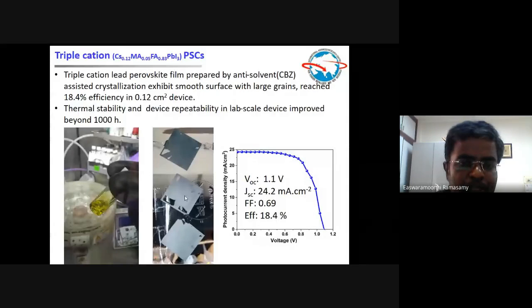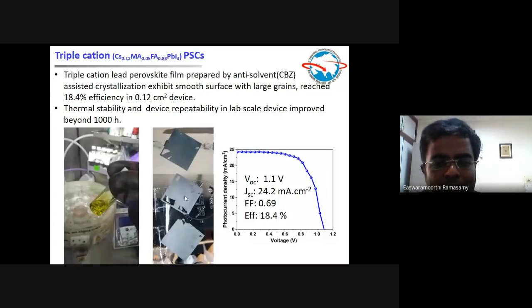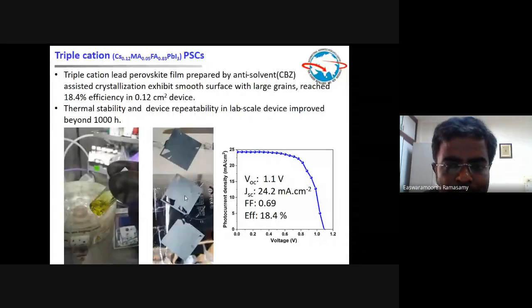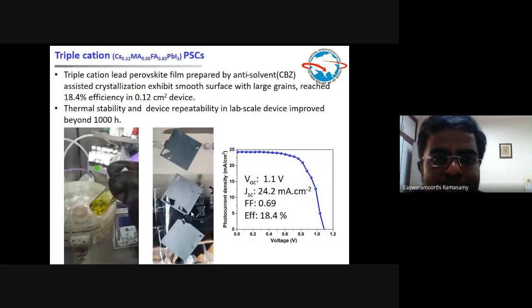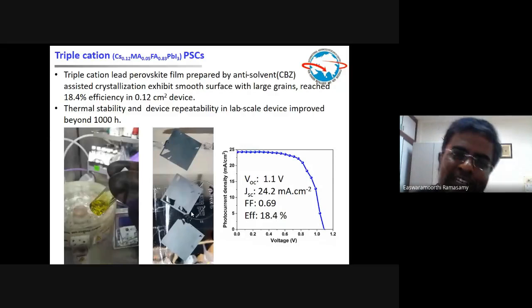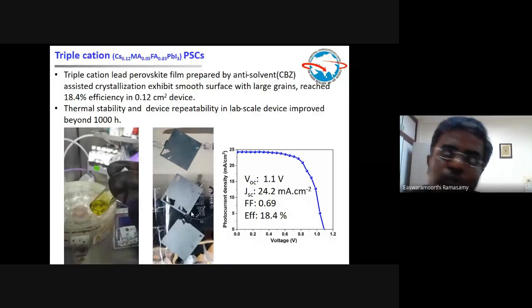Once these films are formed, you have to make a hole transporting material and then cathodes for electron conduction and hole extraction. You can get the device. So the device fabrication is relatively simple and straightforward. In the beginning, we made the methyl ammonium lead iodide perovskite solar cell and got about 16% efficiency. That is the baseline for our activities in 2016.